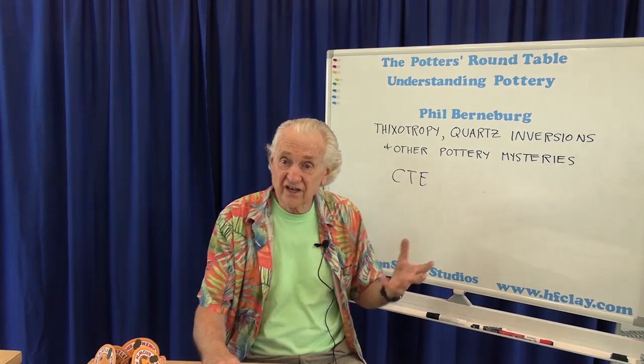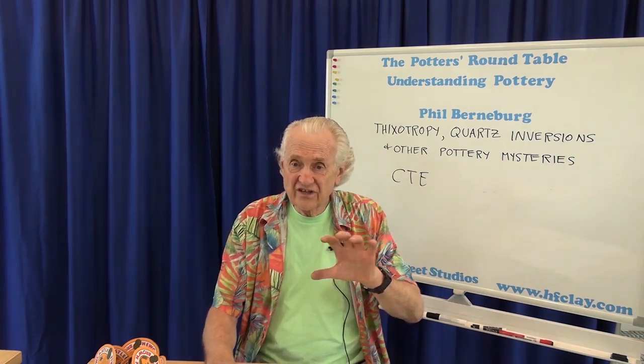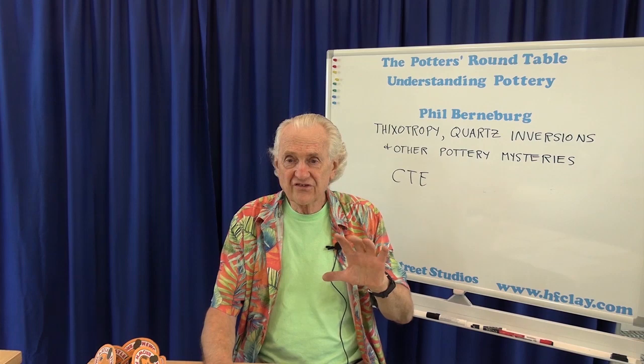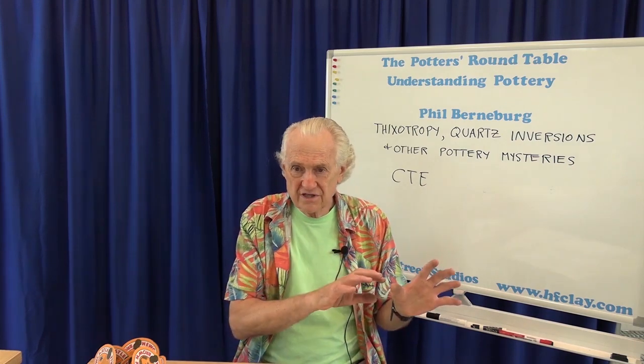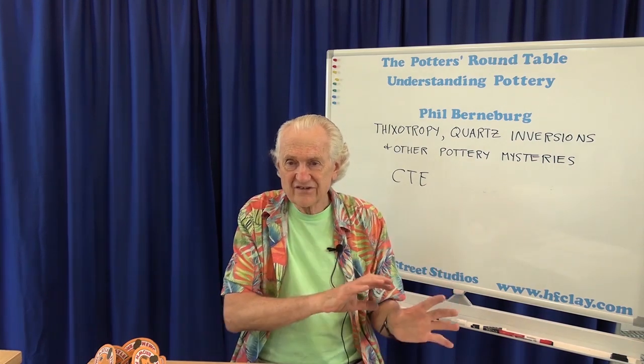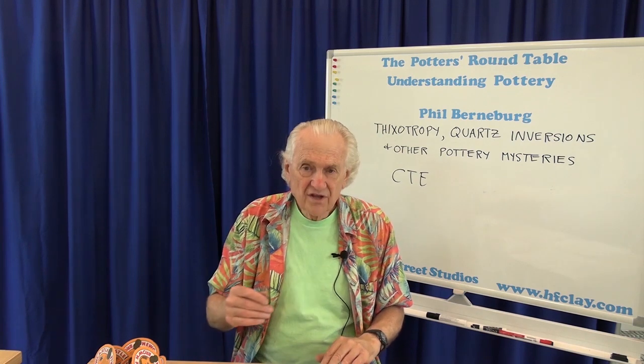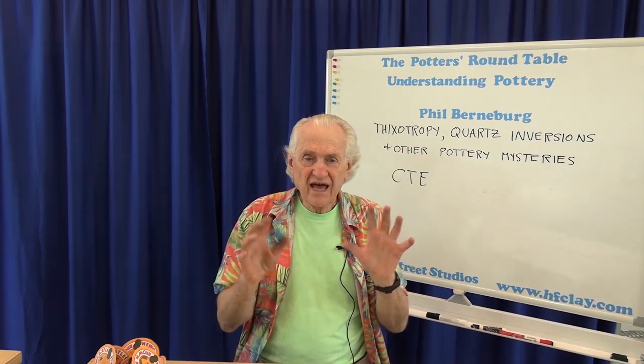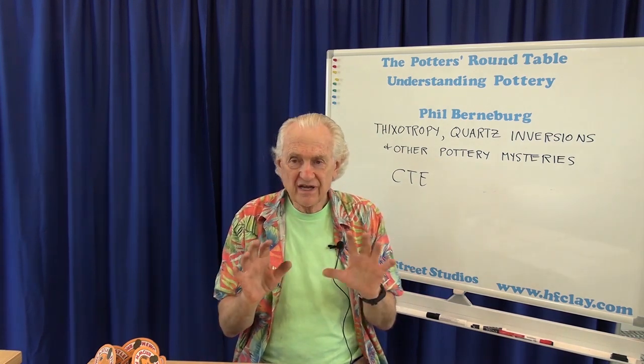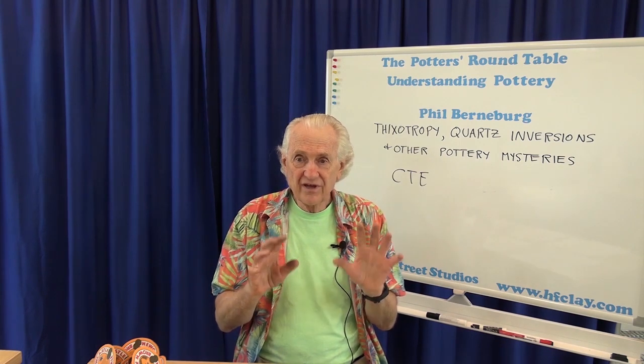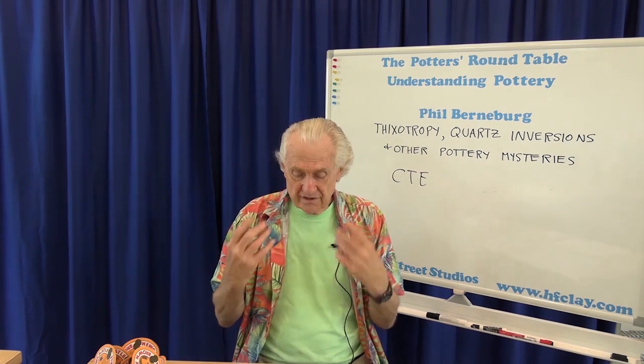as does silicon itself, just the silica. So if I have a glaze that just has a lot of silica in it or fluxes such as lithium, that has a low coefficient of expansion. So that's going to be less likely to craze. So the point is that it's the balance between all the different chemical elements in a glaze that results in the coefficient of expansion that we see.